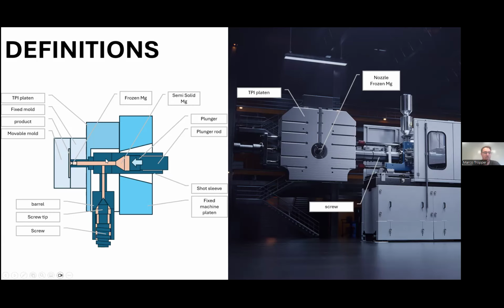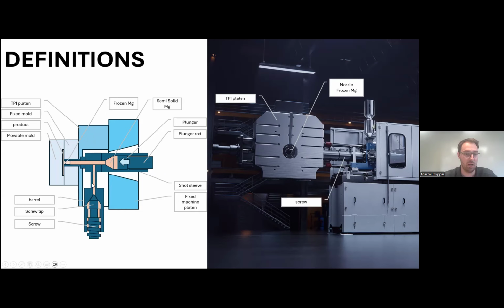And you need it because you have to mount our system, the screw and the shot sleeve, together, and it has to be kept tight here in the front. And on the lower side, you can see here the screw tip that is closing here in the front. So you have to understand, against conventional Thixomolding, we never shoot with the screw. We always shoot with the plunger, and during the shot, we are moving forward with the screw, and with the screw tip, we're closing the screw and the barrel system.